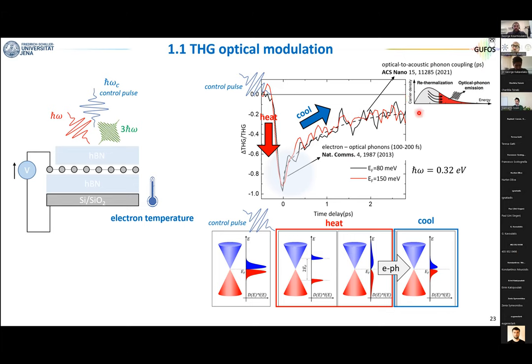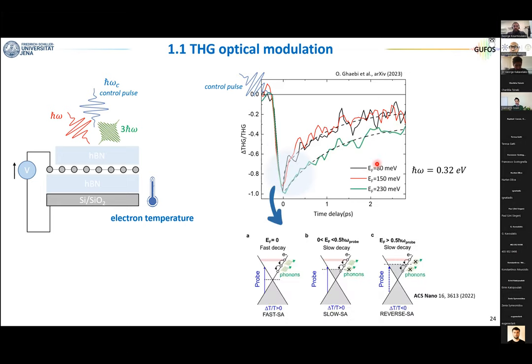But what is interesting for us is that if I now change the Fermi energy, the dynamics change completely. And in particular, the main difference is not in the slow component that is always there, but in this initial fast component that basically disappears as we go to large values of the gate voltage. And now we know why this is happening.